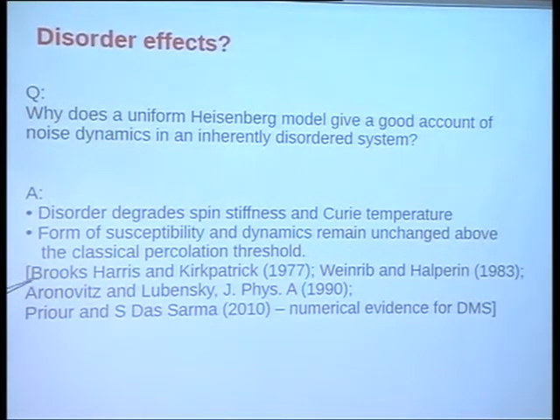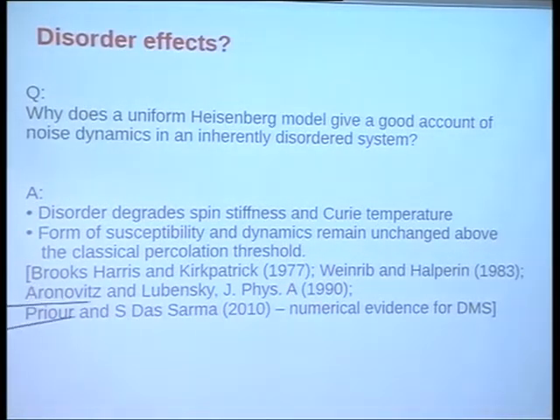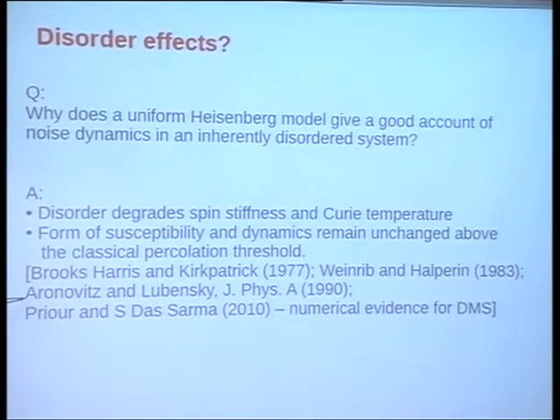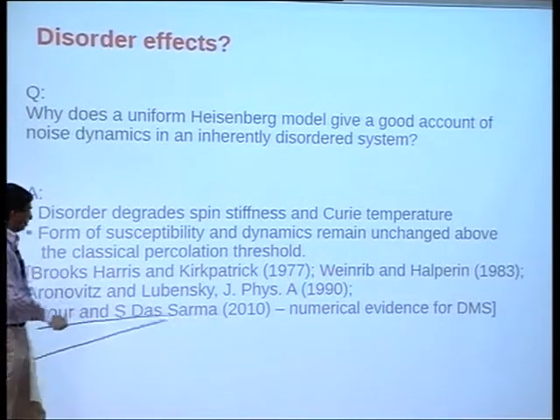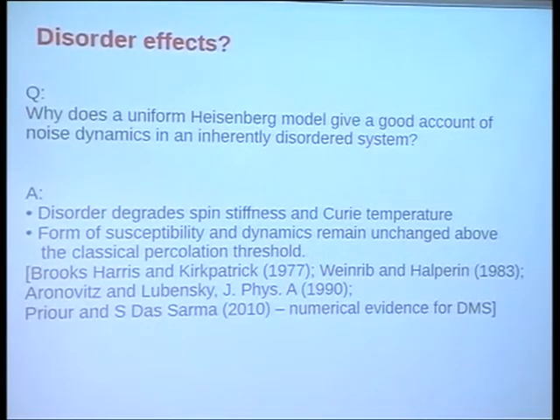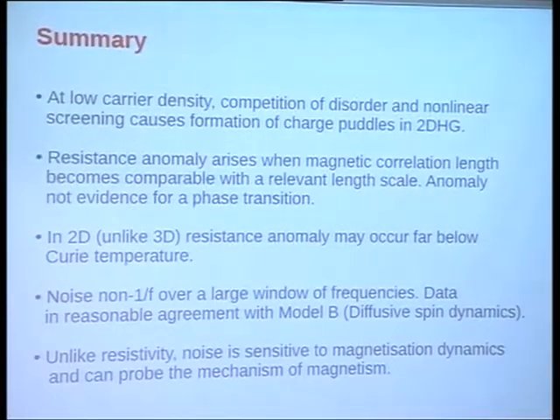This confidence stems from much older works by Brooks, Harris, and Kirkpatrick in 1977. This is the diluted site Heisenberg model. Weinrib and Halperin on the Heisenberg model with correlated patches of TC, so spatially varying TC. And in the context of the 2D Heisenberg model by Aronowitz and Lubensky. And more recently, Priour and Das Sarma have done numerical simulations, and they found that yes, there is degradation of TC and Curie temperature, but you still basically have Brooks-Harris going through fine. And I'm thankful to TVR for bringing to my attention many of these works which were done when he was young. Yeah, when I was just about born.